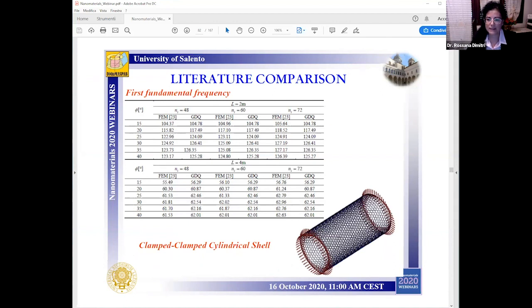And we also validated the proposed approach considering some analytical predictions available from the literature for two different lattice structures with the clamped edges. So this is the first example you can see here that considers a composite anisogrid lattice cylindrical cell made of two regular systems of ribs, I mean the helical and the hoop ribs, with a sufficiently high density, I mean a high number of ribs per unit of length, in line with the continuous treatment of the model, and the comparative evaluation of the natural frequencies is here performed between the GDQ-based equivalent first order shear deformation theory formulation and the finite element analysis proposed in the literature.